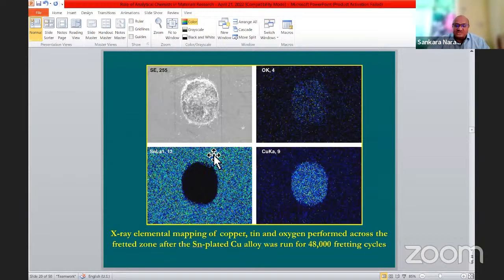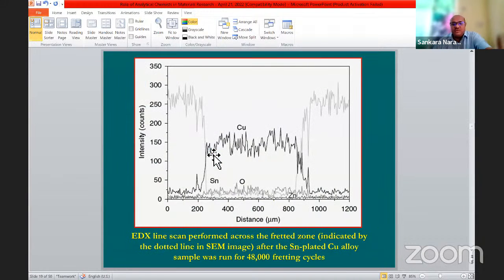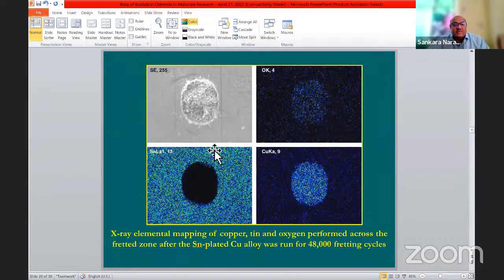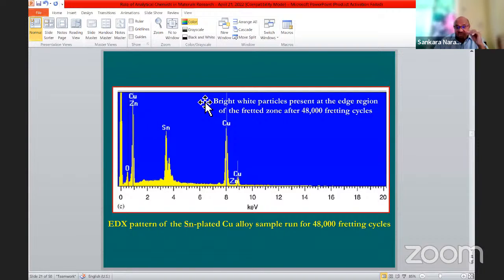You can see that the tin is completely removed. This is subsequently supported by the elemental mapping result. There is no tin here. And there is copper, so the copper is fully exposed in this area, and there is oxygen in this area. So we could have formed copper oxide as well as tin oxide. Particularly the tin oxides are in the surrounding area, and copper and tin oxides are in the middle area. So we can understand the fretting corrosion behavior and how it is getting oxidized.